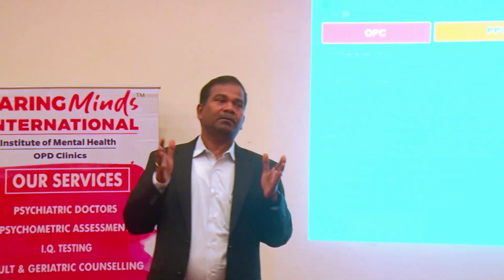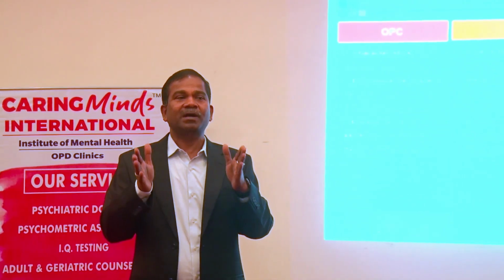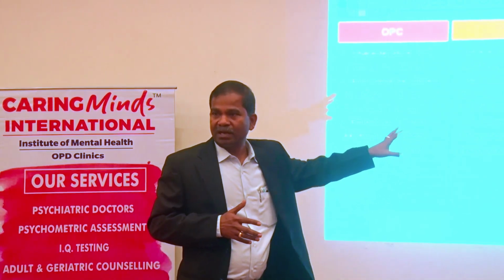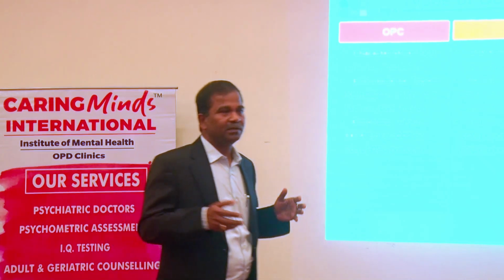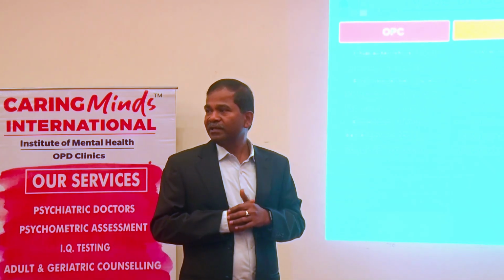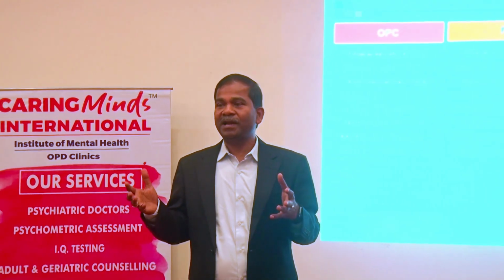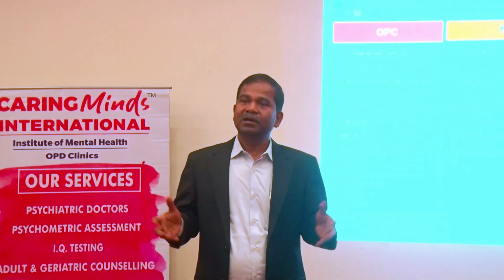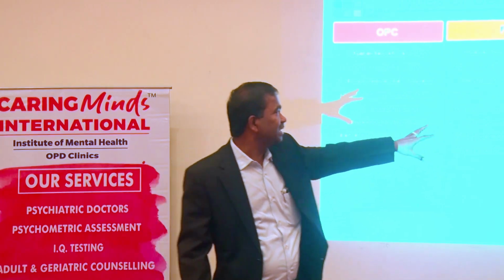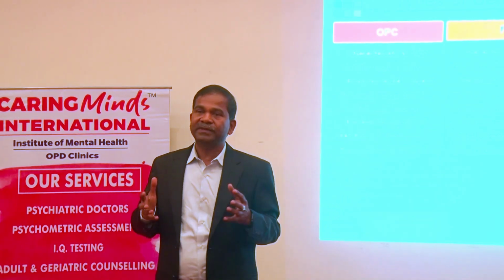Some products where the strength requirement is in between these two, that type of product is composite cement. And this is a new addition, not very new, around 7-8 years back, this was added. So this cement is again a mix of slag and fly ash. Suppose in a steel plant where you have slag and fly ash, we can use a grinding station there and produce this type of cement. That is known as the composite cement. That also is an environment friendly cement.